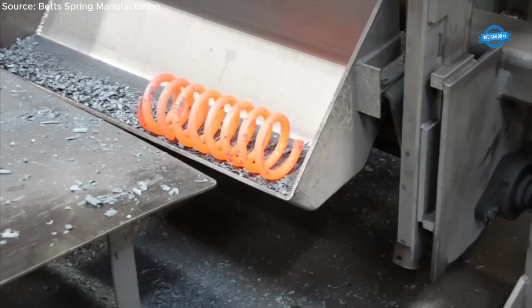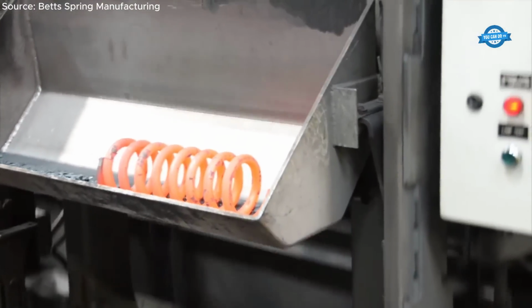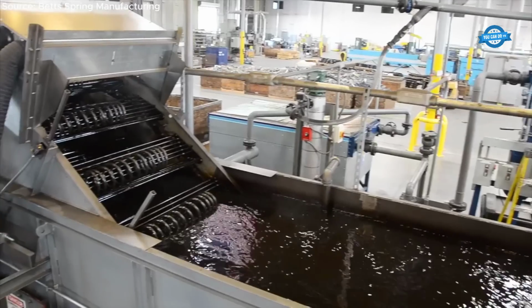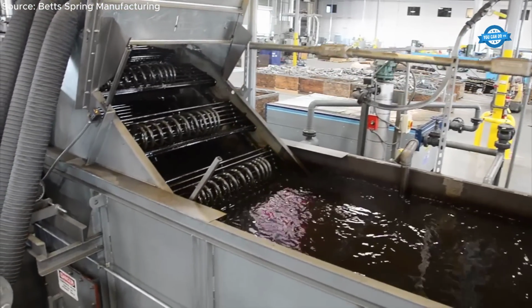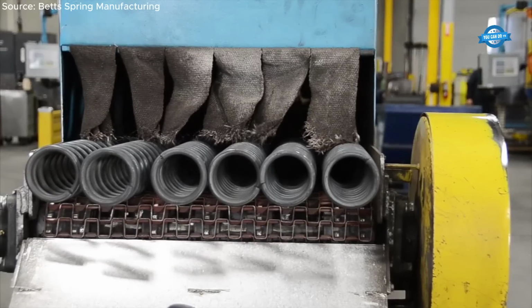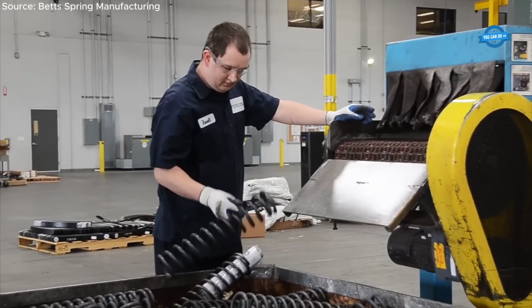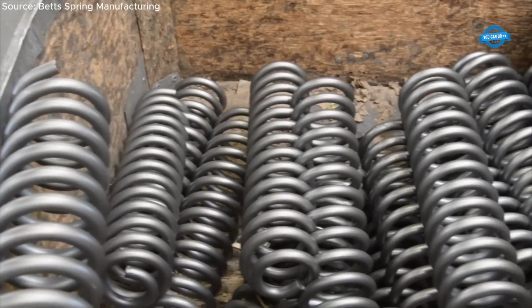Hot winding heats bars to 1750 degrees Fahrenheit in a low-emission furnace, coils them around a mandrel, quenches them in oil, and tempers them, accommodating diameters from 1/2 to 1 3/4 of an inch for diverse applications.